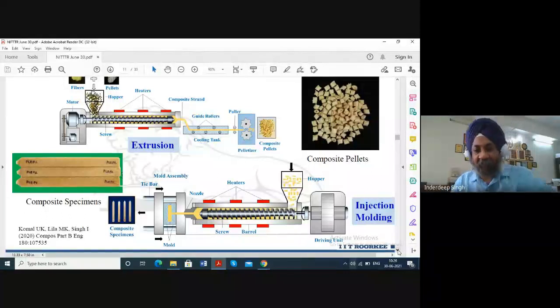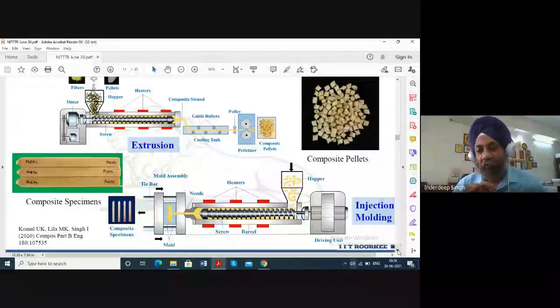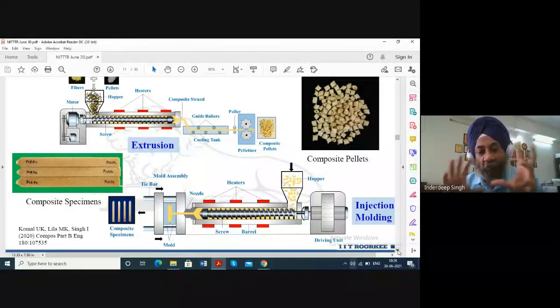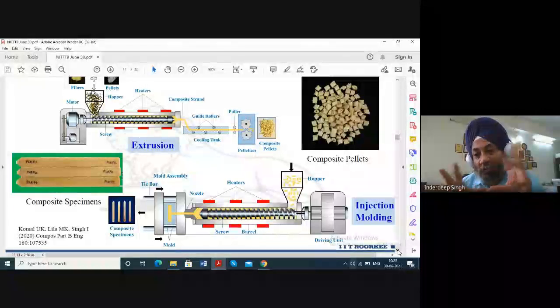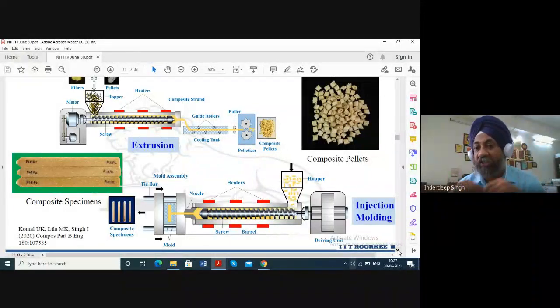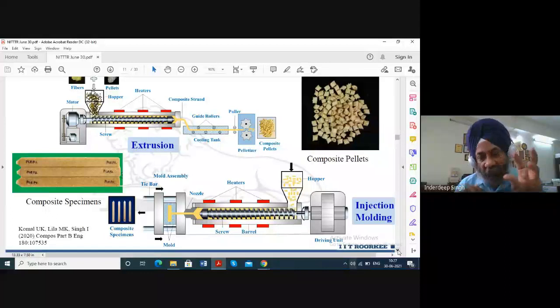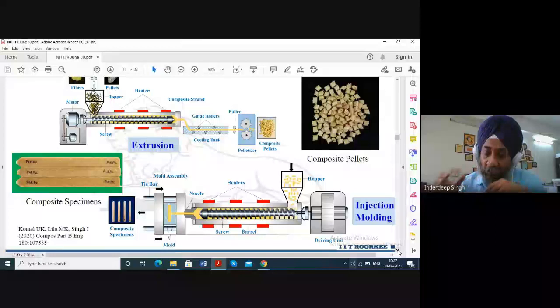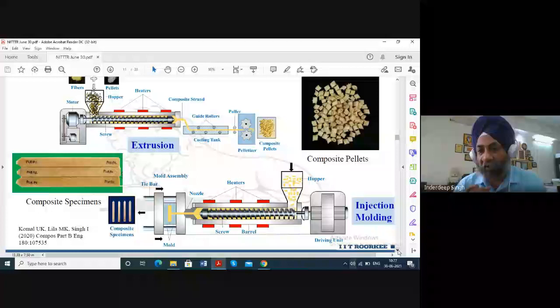So here we see that we have composite pellets. These pellets we are using as feed for our injection molding machine. One of the questions that may arise is why we create these composite pellets first, an additional process, and why not put the fibers and the polymer directly as in the previous process. We have found that compounding helps to improve the interfacial adhesion between the fibers and the polymers, and we have also reported all the findings and how extrusion injection molding is better than conventional or direct injection molding.